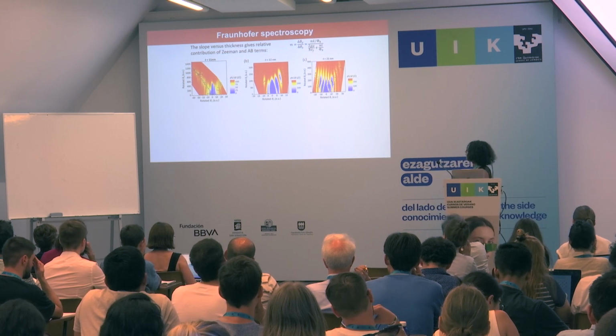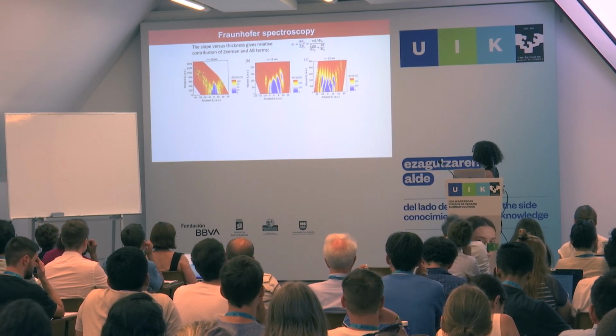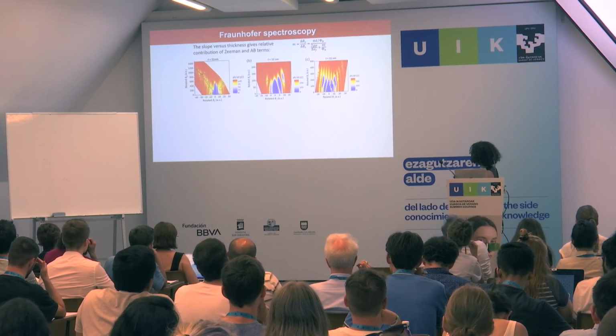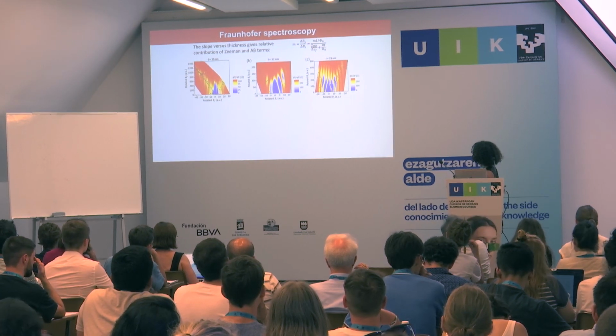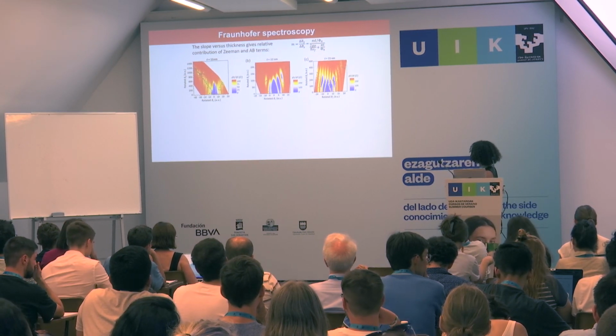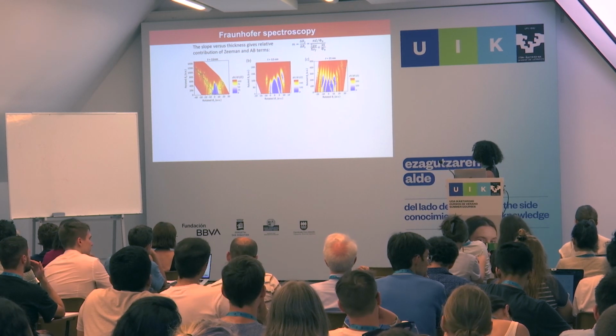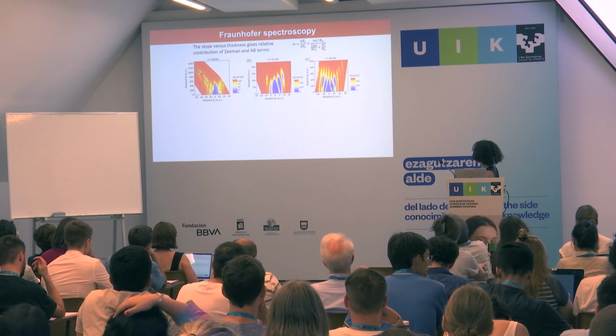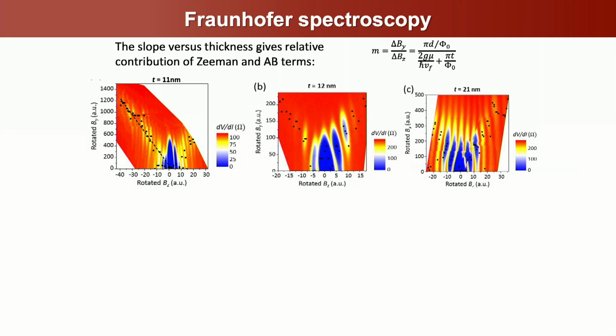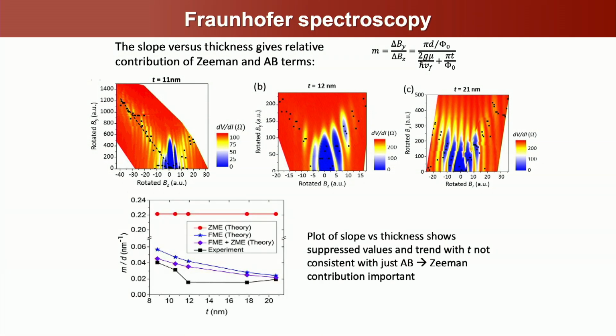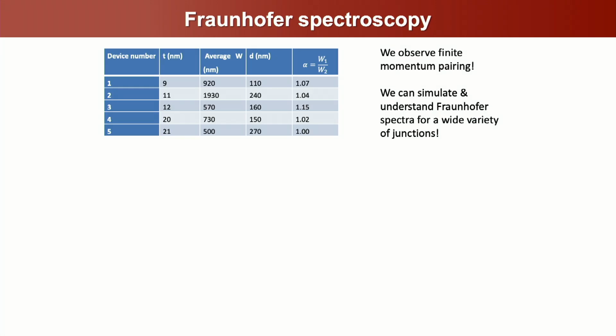We measure it for different thicknesses of samples because the change in the slope we get here of the center of these nodes should tell us the relative contributions of our Zeeman term and our Aharonov-Bohm term, and our Aharonov-Bohm term is related to the thickness. And we can show that as a function of thickness, the Zeeman contribution is important here. Okay, I'm going to end. We can simulate a bunch of different ones. It was cool. It's fun.